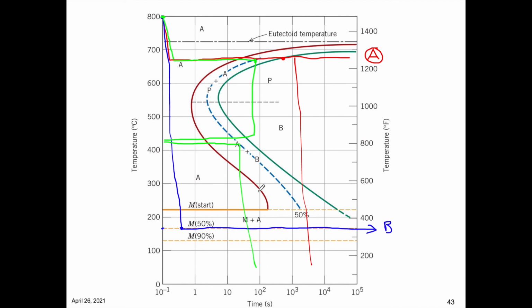So that's a multi-step process, obviously, where you do an initial isothermal transformation to get 50% coarse pearlite, and then we want to rapidly quench to a temperature in the bainite region. That reaction starts over again, but we only want 50%, so we only go to this 50% line, and that will give us 50% of 50, which is 25, and then the remaining 25% austenite is done by quenching, right?